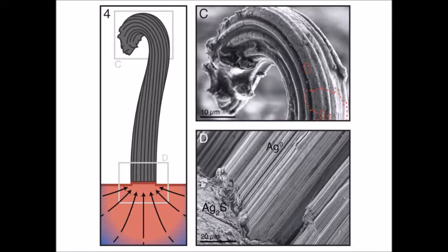Now, again, the striations that occur are essentially superimposed on this polycrystalline elongate mass of wire silver. And those striations continue down all the way to the base of the silver sulfide, where the actual crystal growth is taking place. So crystal growth in the case of wire silver is at the interface between the wire itself and the matrix or the acanthite.